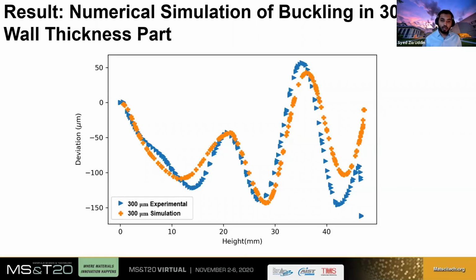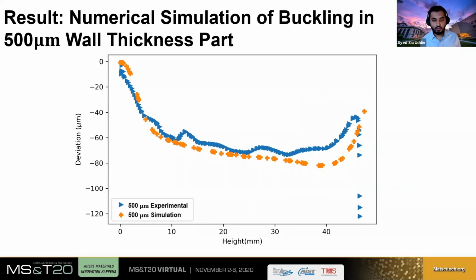particularly for predicting buckling behavior in thin wall structures and finding out the root cause of buckling and how we can prevent them. The same holds true for the 500 micron wall thickness. We have got very good correspondence between the experimental and simulation results as well.